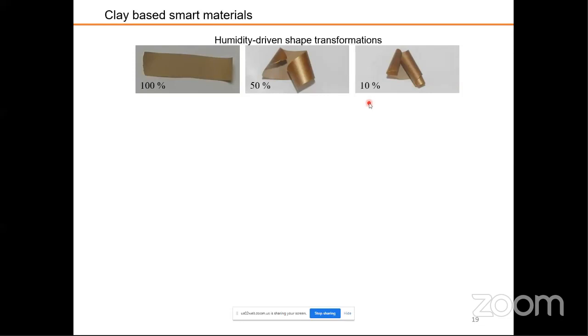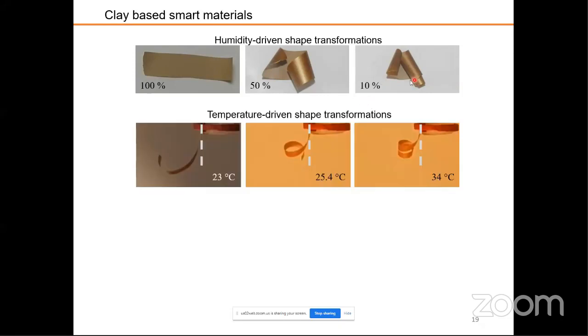And it's very, very repeatable. Every time we get back to 100% humidity, it's flat again, and again it rolls up the same way at 50% and 10%, completely rolled up. Similarly, it is also very sensitive to temperature. At 23 degrees centigrade, it looks like this band shape, but when you increase the temperature to 25 and 34 degrees, it's completely rolled up like a spring.